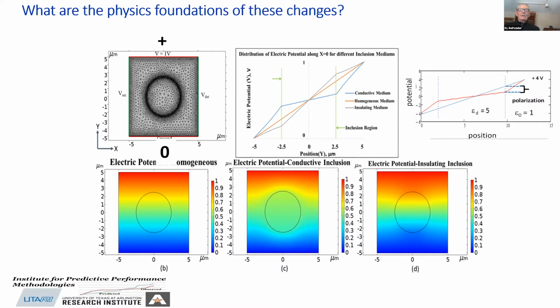And you would expect that the change in voltage must be uniform from point to point, since, as we saw in our expression, the material is uniform. Well, let's say that the material inside is conductive. Let's say a chunk of carbon material, which is one of the experiments we did. Then, if it's conductive, delta voltage must be less, right? Because now we have a larger term in front of that thing. So the slope must be less. It's conductive. You would expect less change in voltage. If it was a copper wire, it'd be 0 change.